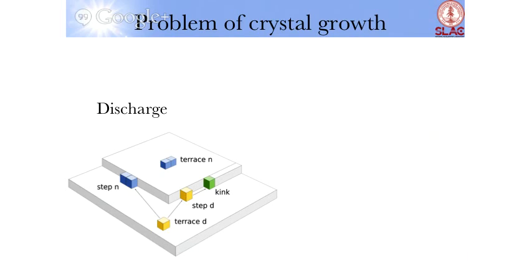So this is nucleating on a terrace to grow. You could diffuse from a terrace to a step site and then nucleate there, or you could diffuse from a step site to a kink site and nucleate there. But in electrochemical crystal growth, what we are after is essentially the ones that have the lowest overpotential, because those will be the ones that are dominant in rate. Because when you apply a galvanostatic condition, those are the ones that have the lowest voltage penalty that one needs to pay. Those are the growth modes that will be active.